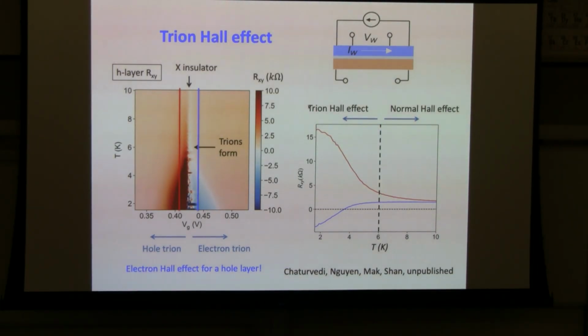But below the temperature that the trions form, the red curve here just goes to a much higher Hall resistance. And what's even more surprising is that the Hall resistance of the hole layer would actually change sign. When you measure the Hall effect of a hole layer, it turns into like an electron layer. So it's quite a surprising finding. And the only way that we can make sense of this data is, again, the formation of the trions. Because in this case, you have electron trions. The 2 electrons will drag the hole to flow in the opposite direction, and that's how you get a change in sign of the Hall effect, even though you are measuring the Hall effect of a hole layer.